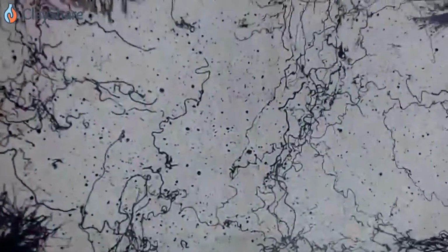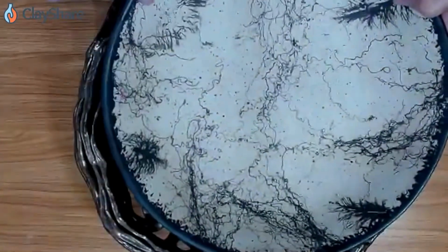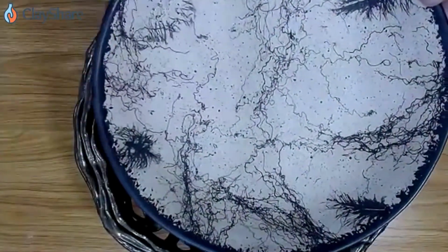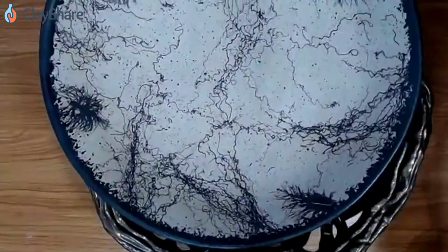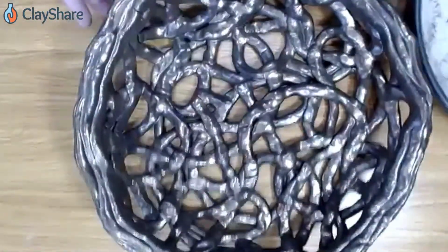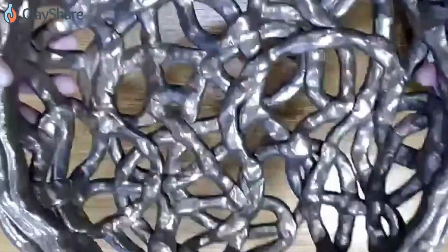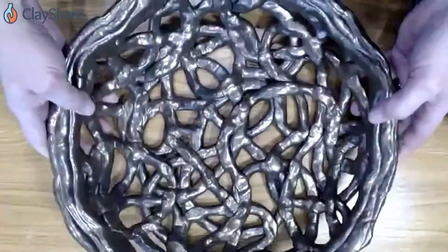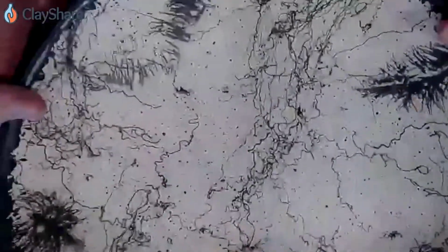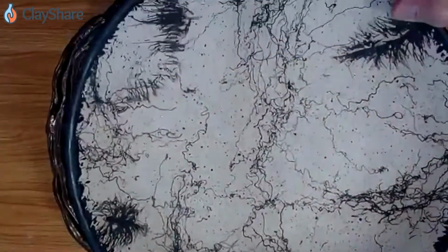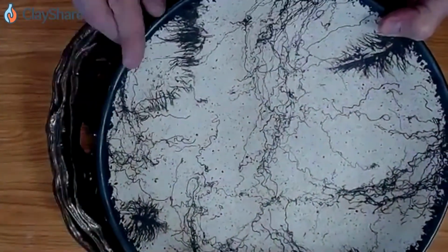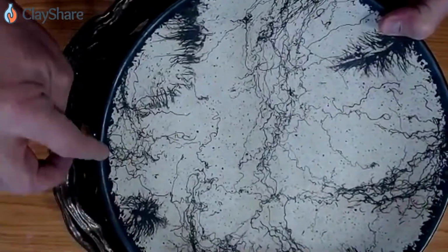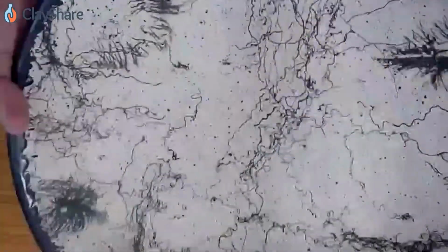Mako speckled buff engobe. And what I did is around the edge of it and on the inside, I sponged a glaze called antique brass, which is this bowl below it. It's a metallic goldy brass glaze. And so I thought, oh, I'm going to speckle that and get all those little speckles in there with that glaze. And then I sponged on the edge. But what happens when you take that glaze back to that 900-degree temperature, it becomes more matte and you lose some of the metallic, but the little speckles in there still really sparkle on that piece.